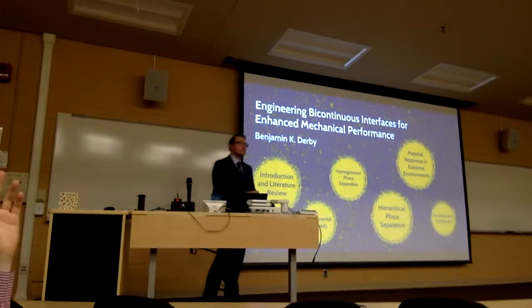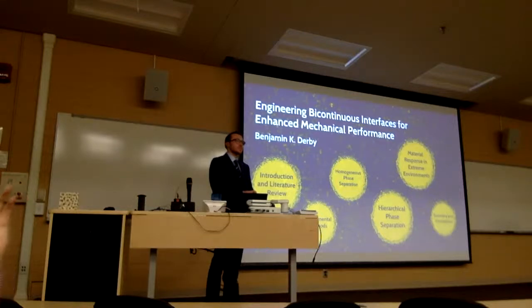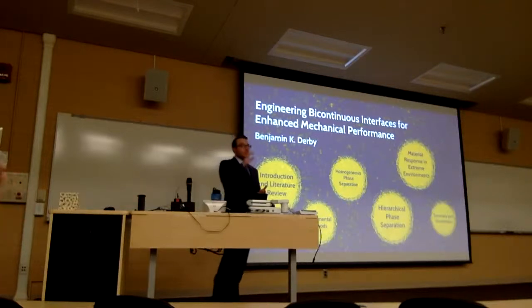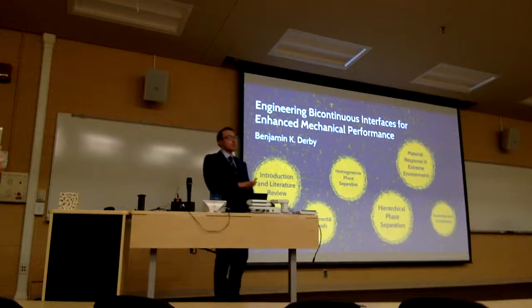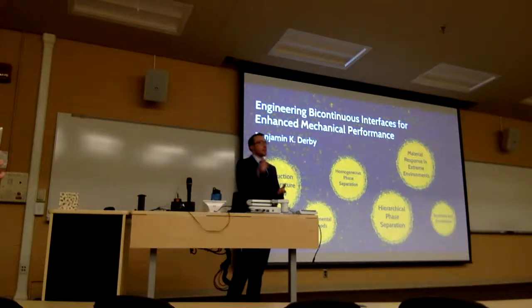I was curious, you have these tiny bubbles that look like they're nanometer dimension at the interfaces. I just wondered how you knew for sure, because those STEM images, are you just going by the contrast? Those are where I showed the bubbles inside the structure. Those are bright field TEM images. By Fresnel contrast, we predict that the contrast changes when there are bubbles in the structure.